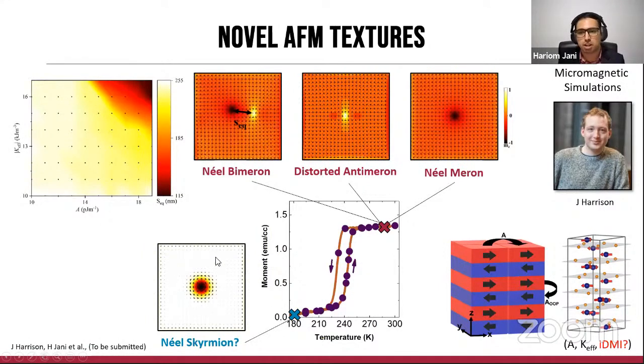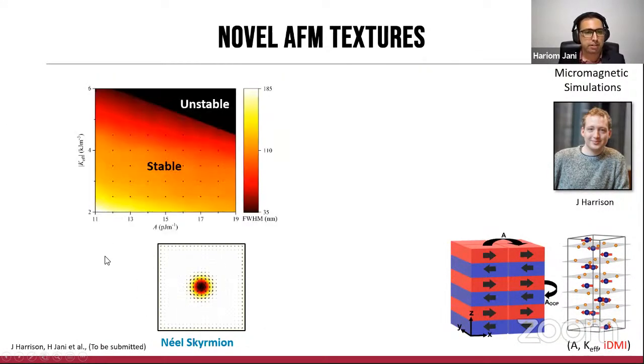And it turns out that by the combination of A, K and D, it is actually possible to realize these Néel skyrmions. First and foremost, shown here is one particular example of the phase diagram for a value of the Dzyaloshinskii-Moriya exchange of 1 millijoule per meter squared, which is very standard in the spintronics community. And we observed that in a certain regime of A and K accessible in the material parameters, we actually are able to stabilize antiferromagnetic skyrmions.